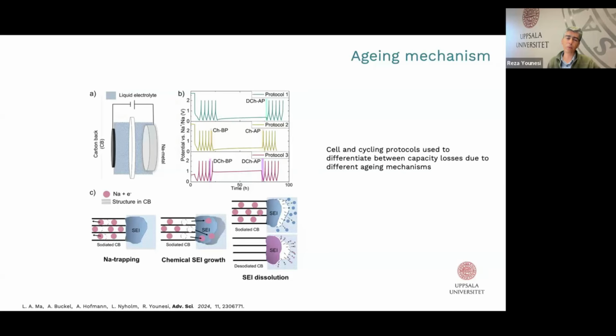So by using different protocols, we try to understand different aging mechanisms related to SEI and related to the negative electrode. Below, you see a schematic of a few possible agings related to the negative electrode. On the left, you see that when the electrode is sodiated and we pause the cell, and after the pause, we see that some sodium is lost.